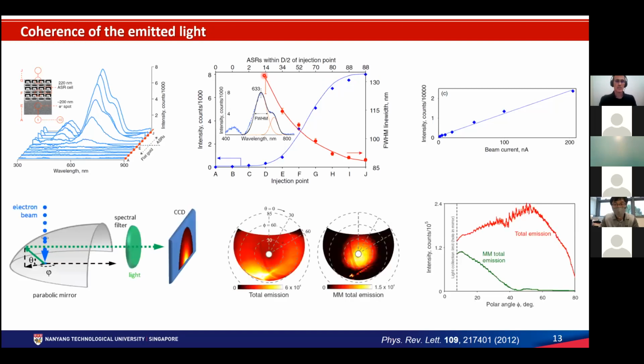We also tested the sample for spatial coherence. We did the same experiment, but this time, instead of looking at the spectrum, we filter at the main peak of emission, and then we take an image directly on the CCD. When we look at the image of the emission of the metamaterial array itself, you can see that it's mainly collimated around the center. The divergence is not very small, but it's not very high. It's about 30 to 40 degrees. So this means that the material is starting to build spatial coherence in its emission.